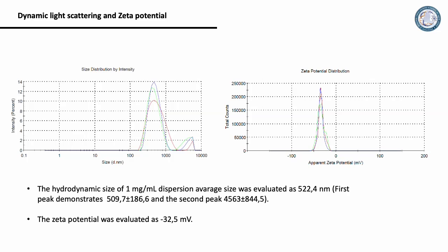The DLS measurements of cerium oxide nanoparticles also revealed an aggregation tendency with the hydrodynamic size of a 1 mg per milliliter dispersion. Average size was evaluated as 522 nanometers. The zeta potential value of minus 32.5 millivolts clearly indicates that biosynthesized cerium oxide nanoparticles have good stability. The high negative value of zeta potential confirms that capping particles are present on the surface of nanoparticles, mainly comprised of negatively charged groups, which give moderate stability to the nanoparticles. The proteins in the extract are responsible for reducing metal ions. They are efficient in stabilizing the synthesized nanoparticles.